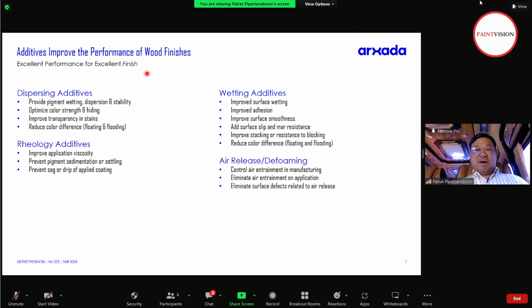Our products from the Arxada portfolio include dispersing additive, which helps with wetting and dispersing and controls stability of your pigment paste system or your coating system. It optimizes color strength and also hiding after tinting, especially if you use some stain, which is a transparent pigment. It also improves transparency of your transparent stain system. It also reduces color difference, meaning color floating and color flooding are going to be no more with your coating system.